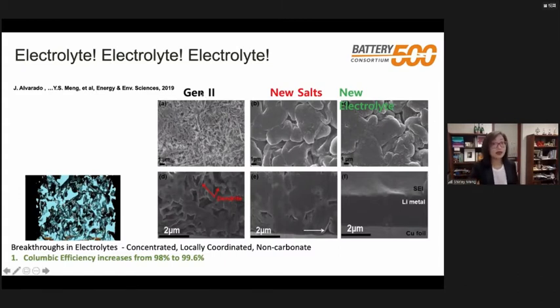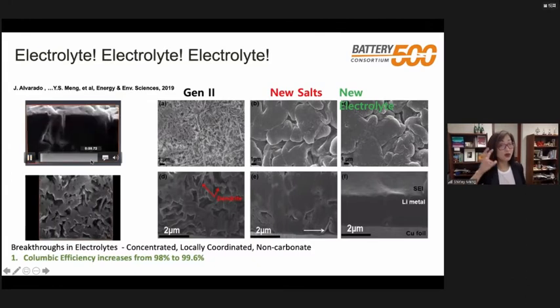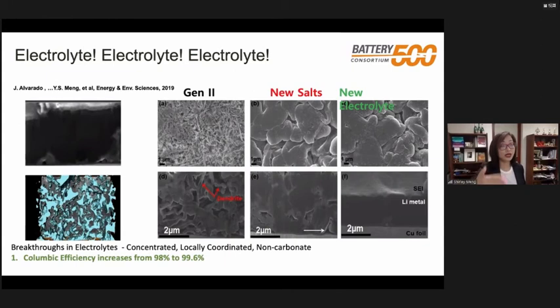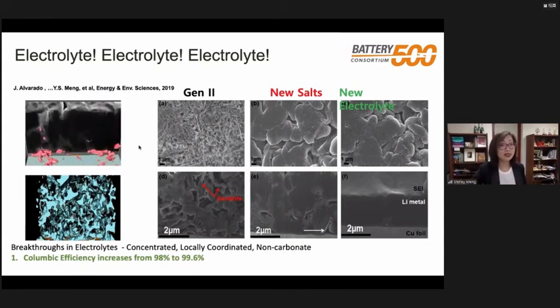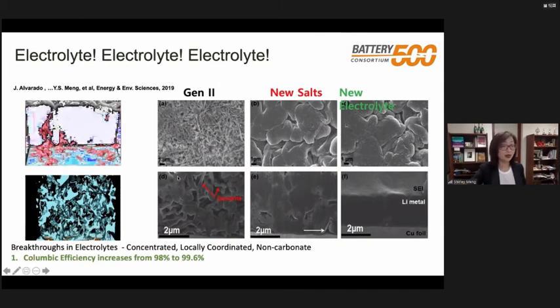In the electrolyte that scientists have been optimizing for graphite anodes, the carbonate electrolyte, we also call it the Gen 2 electrolyte, the morphology is terrible, okay? You can take the top view and the cross-section view, and do the three-dimensional cut. It's really quite terrible. And the performance, the efficiency number is very low. 98% means after a few 50 cycles, you have no capacity anymore. Everything is lost, right? When you have the new electrolyte, based on what Pacific Northwest National Lab has reported, the ether-based electrolyte, the morphology completely changed. You have very dense lithium. I mean, it's not perfect yet. I will talk to you later about how to make it more perfectly dense, but these cells are reasonably much, much better than the carbonate electrolyte, right?